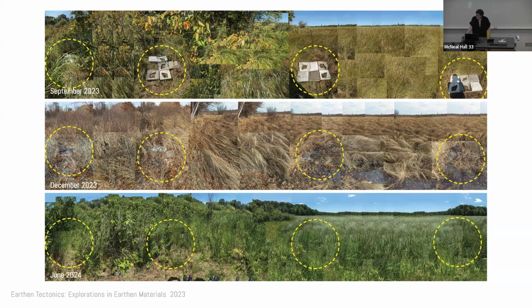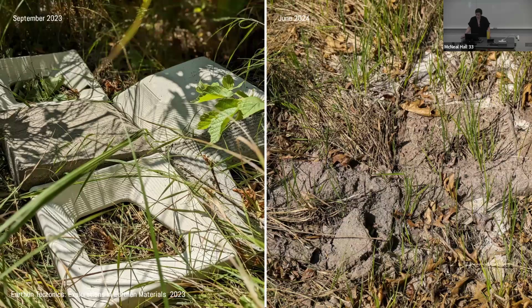The 24 modules were installed in September 2023 at the edge of a marsh in 4 locations, moving from submerged up the slope. By December 2023, after a very wet fall, many tiles had already disintegrated and were sitting in an inch of frozen water. By summer 2024, many were engulfed by emergent vegetation. The modules degraded at varying rates, and even after the first growing season, we began to see microecologies and microhydrologies shifting, new vegetation, leaf litter, and when you got close enough, insects.